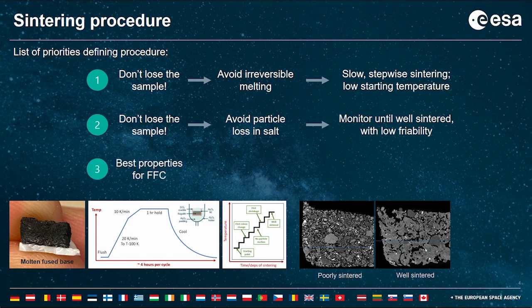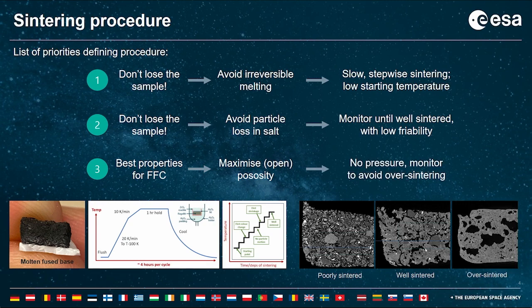And then the third priority, we were wanting the best properties for FFC molten salt reduction. And so we want to maximize the porosity and maximize open porosity. And so we don't apply any pressure to the material. So these materials would be terrible in construction. They have bad mechanical properties. We're aiming for porosity. And then we want to avoid over-sintering, so we don't want a glassy material with lots of closed pores.